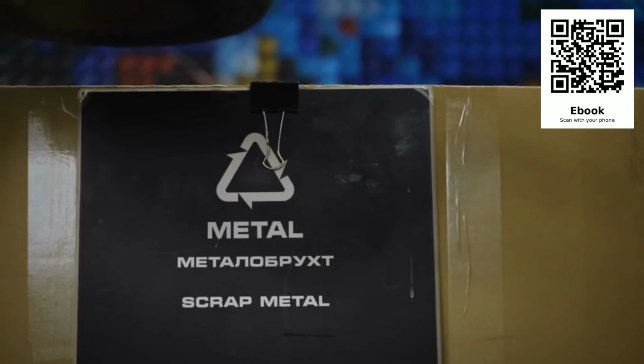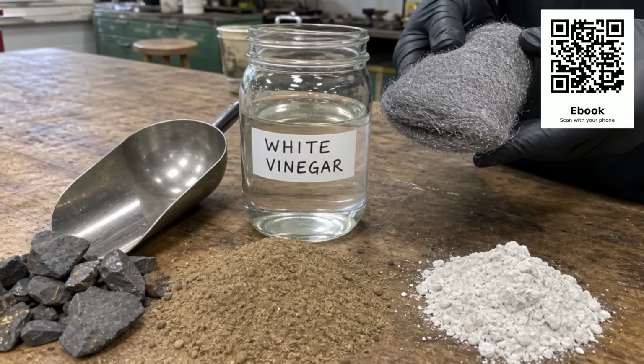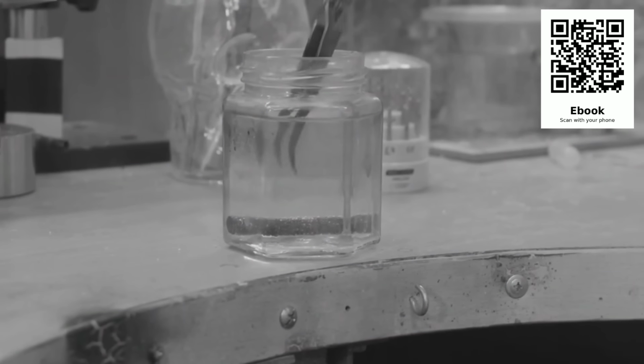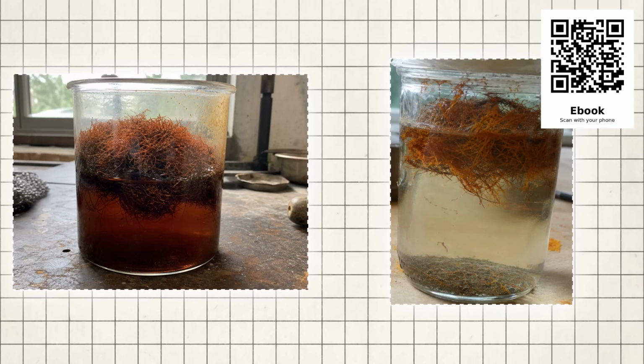The iron source matters too. I have had men in the comments tell me they use steel wool, and steel wool does work, but it works too fast because it has so much surface area. You end up with a solution that is saturated with iron acetate in the first hour, and then the rest of the steel wool just sits there rusting on top of your liquid instead of dissolving into it.